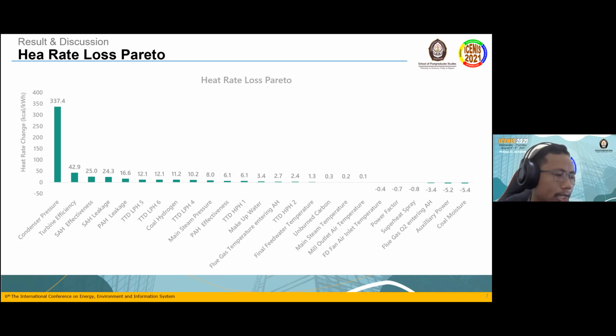The next factor is that heat rate increase was also caused by the rise of terminal temperature difference, or TTD, of high pressure heater number 1, high pressure heater number 2, and low pressure heater number 4. In addition, low pressure heaters number 5 and 6 being out of service due to extraction valve failure also contributed to the turbine heat rate increase.